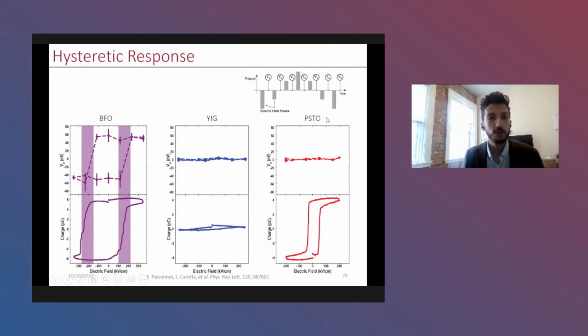We can do some control measurements, for example, on YIG, which is not a ferroelectric, so we don't expect any sort of ferroelectric hysteresis, and thus we don't see any non-local voltage change. So we know it's not any circuitry of the system that's causing it. We can also do this on a ferroelectric which is not magnetic, which has, of course, a ferroelectric hysteresis loop, but has no non-local change either. So this proves that it's not a dielectric effect enhanced from the ferroelectricity that's causing this.